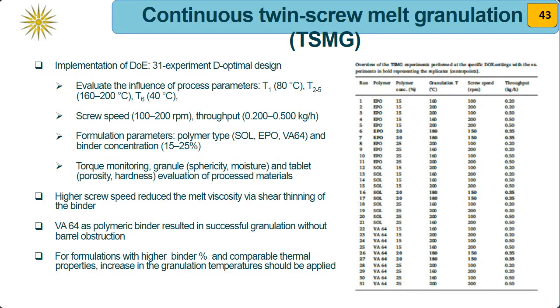The authors implemented a design of experiment with 31 different runs. As you can see in the right table, the polymer grade was investigated. The polymer concentration was also taken into account, as well as the granulation temperature, the screw speed, and the throughput of the process. The torque monitoring, the granule sphericity and moisture, and also the tablet porosity and hardness were used to evaluate the whole process during the granulation and the tableting of the obtained granules.